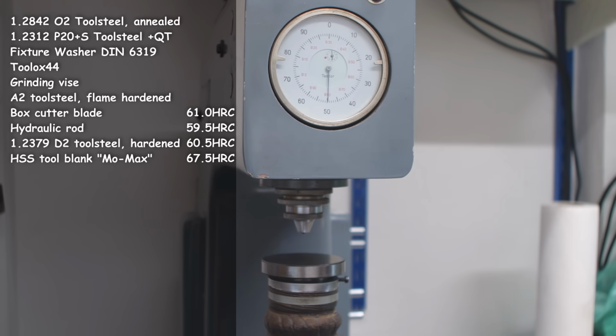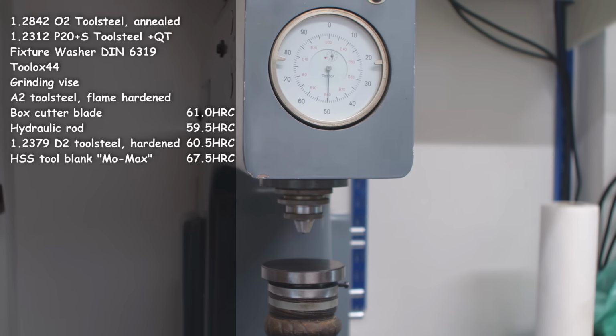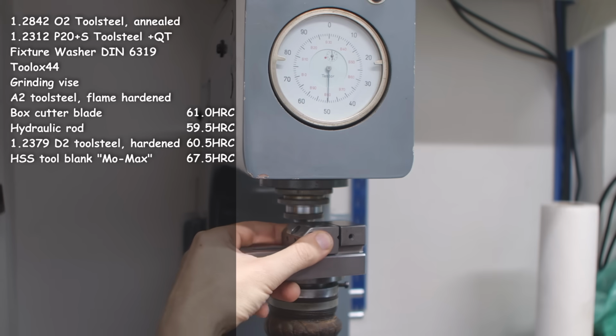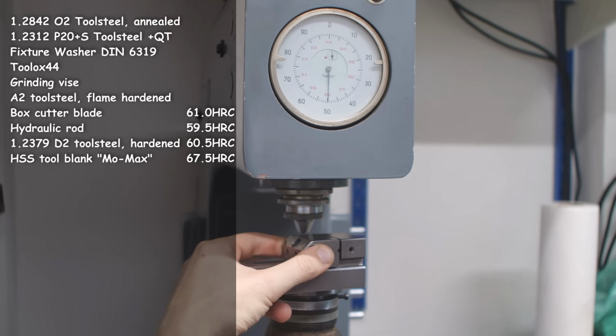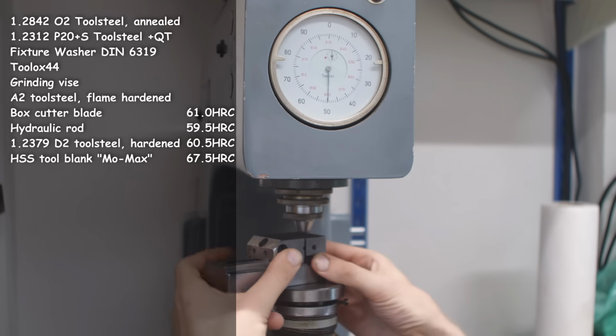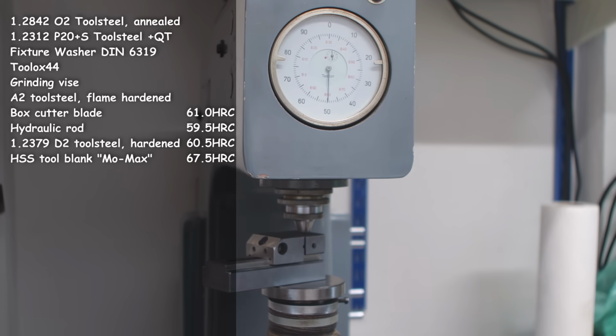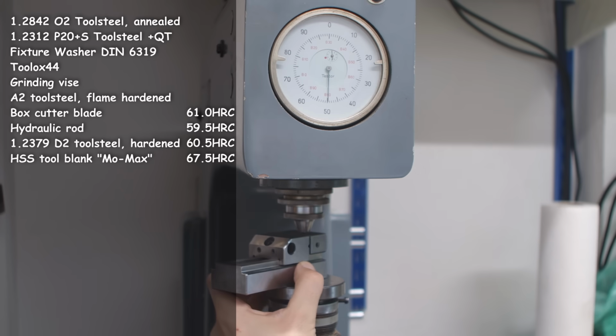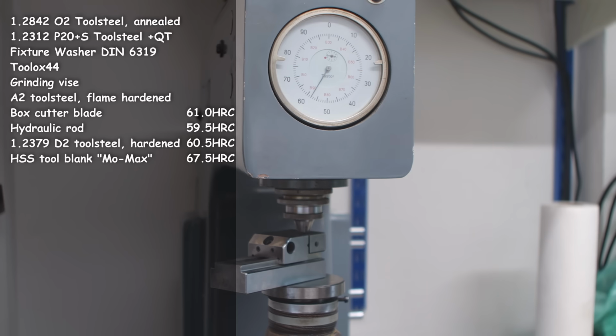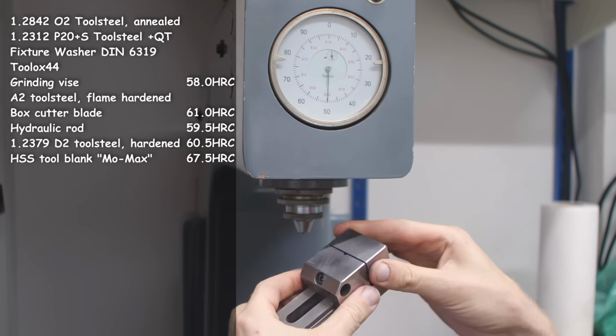Now, cheap grinding vises. I do like cheap grinding vises. They have been very good to me from a performance standpoint, and they last quite a long time because they usually have a decent heat treat. So this one needs a regrind anyways, because this is the one I use to hold stones when I grind them. There is some severe wear on this one, and I don't mind putting some indentations on the top of it. Okay, it has settled out. That's 58 Rockwell C. As I said, it's a very decent heat treat. A file won't touch this.